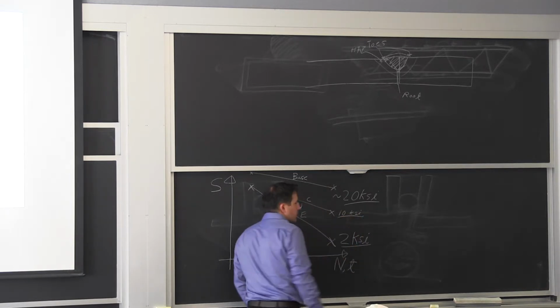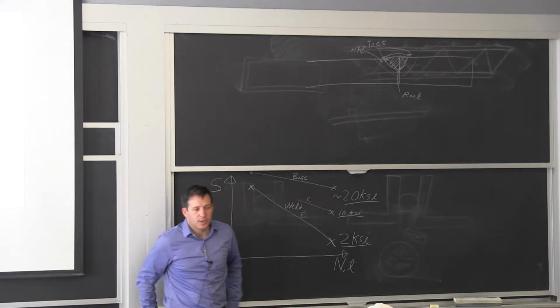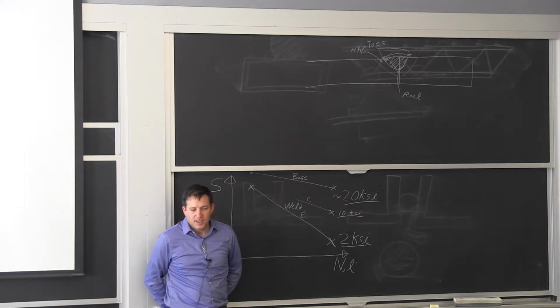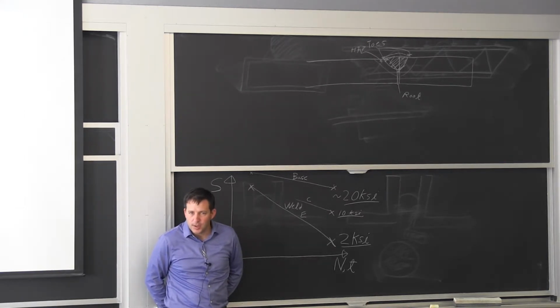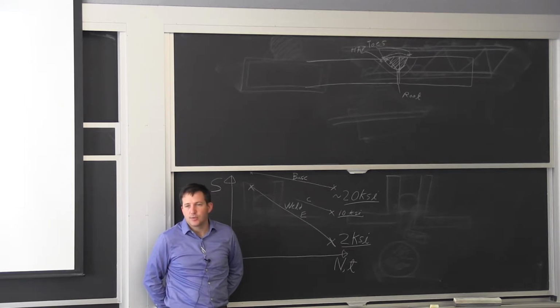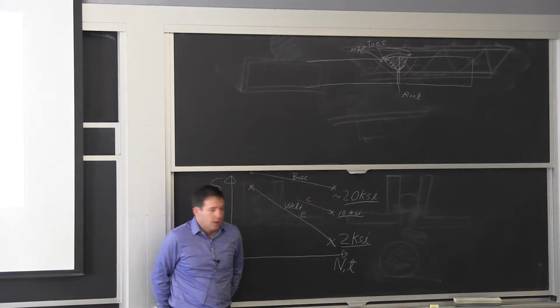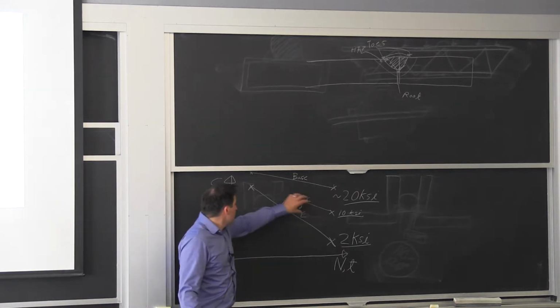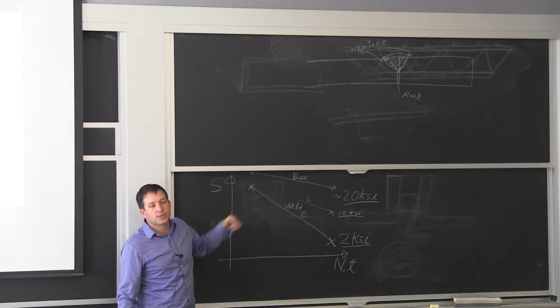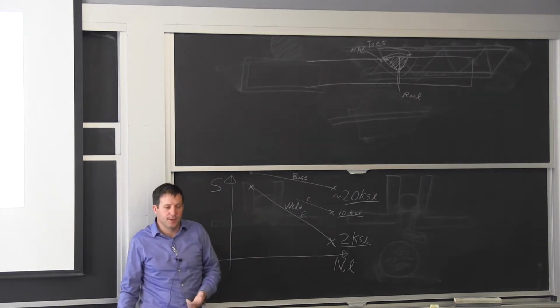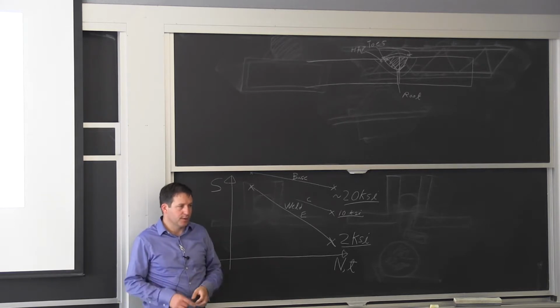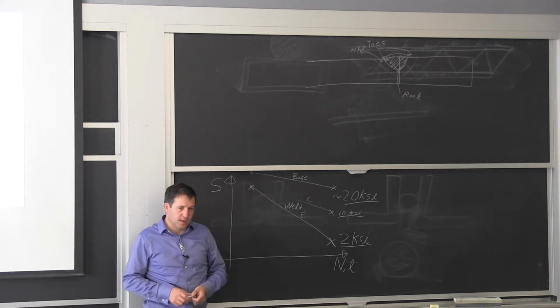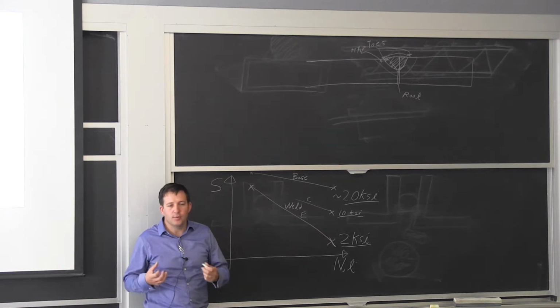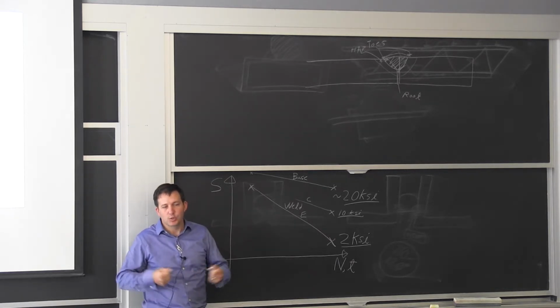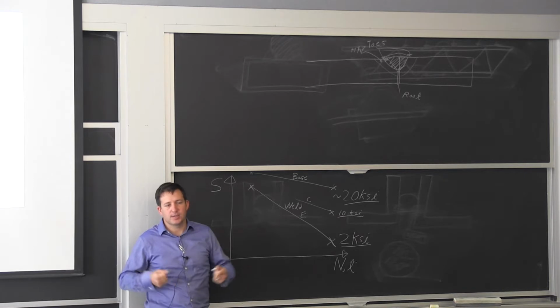So this is the huge range for a welded joint, and really it's a function of the geometry and the loading, of how much of a knockdown factor you get. You have these knockdown factors here on the base material too, but those are closer to a factor of 50% change if you're welded or not. Because if it's done correctly, if you have the fusion, you can take a weld and stretch it once. It will take it. The problem is when you start doing it repeatedly.